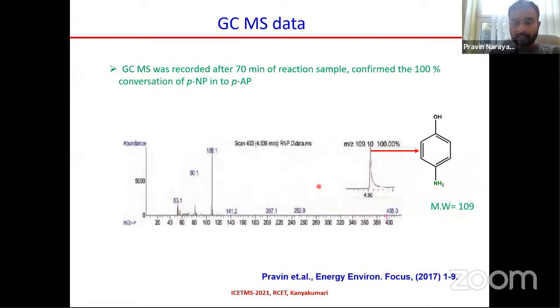And this percentage of conversion has been confirmed by gas chromatography-mass spectrometry. The GC-MS was recorded for the reaction sample after 70 minutes, and confirmed 100% conversion of para-nitrophenol into para-aminophenol based on the molecular weight. You can see the molecular weight of para-aminophenol is 109, and the exact peak appeared at 109. So 100% conversion happened in this reaction. The catalyst is very efficient.